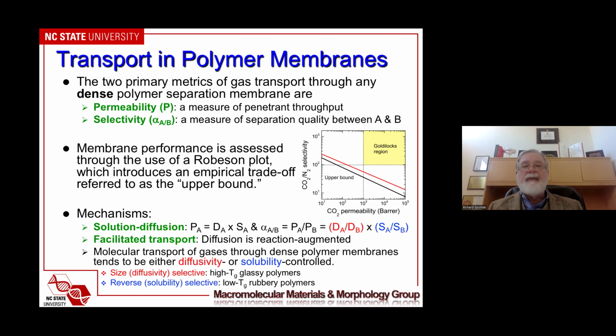The mechanisms for transport are either solution diffusion, which is the most common. In this case, in the Fickian diffusive regime, our permeability is simply the product of diffusion and solubility. Or we have facilitated transport where the diffusion is reaction augmented. And we usually talk about transport being diffusion controlled or solubility controlled. And diffusion controlled membranes are typically glassy polymers, whereas solubility controlled membranes are usually rubbery materials.